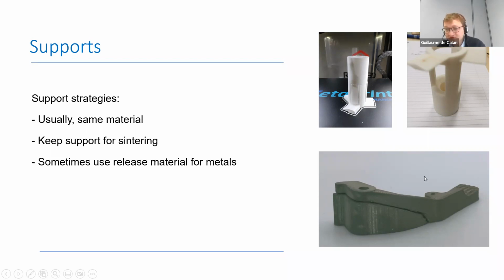For metal, it's even more crucial because metal is sintered at a temperature which is really very, very close to the softening temperature of metal and even the melting temperature of metal. So the metal is literally soft when you're at sintering temperature. So you need those supports to stay there during sintering if you have significant overhangs. In some cases, you may need to use a release material between the support and the part to avoid the part sticking to the support. We have a few methods to do that. We can use, of course, a ceramic filament, but more simply, we usually just put a bit of ceramic powder between the support and the part, and that really works very well.